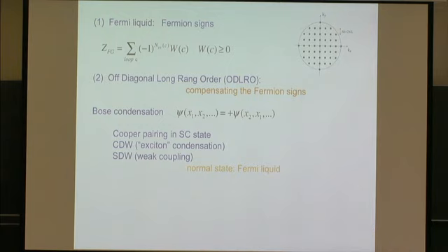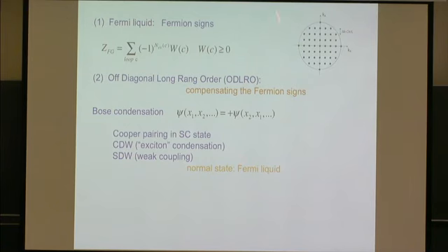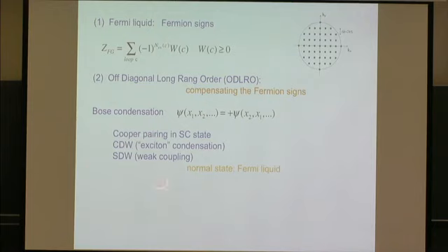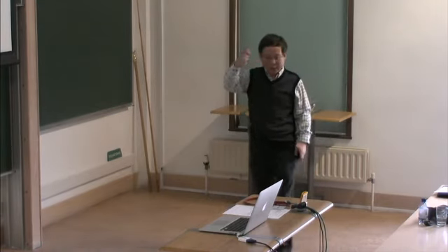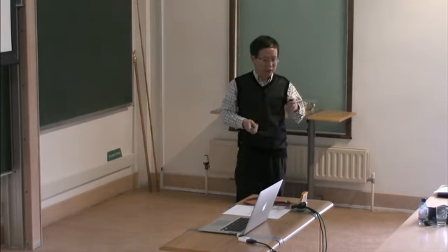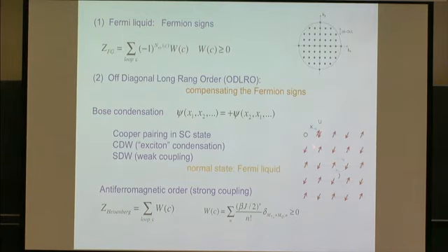But the problem of all this weak coupling case is that if your temperature is high enough to drive this order away, then because there's a large Fermi sea there, the fermion sign is back, and the normal state is a Fermi liquid, just like Subir just pointed out. This is all the weak coupling case. You cannot get rid of fermion signs. But now let's imagine, as I have mentioned, that if we increase the U large enough at half filling, we have another limit where all the spins are localized. This is described by the Heisenberg model.